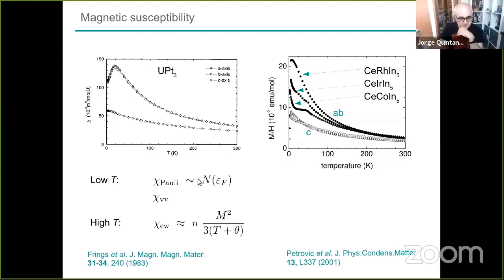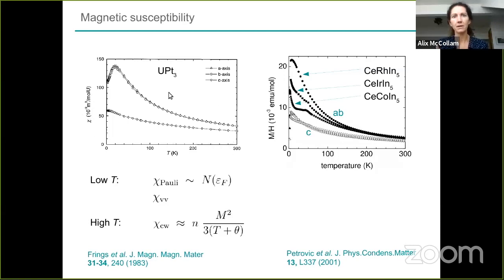Thanks. Okay, this is an example of the susceptibility. So this is chi versus temperature. Again, this is uranium platinum 3. This is a nice Curie-Weiss behavior at high temperature, and then at low temperature you see a Pauli dependence here. This is proportional to the density of states at the Fermi energy.